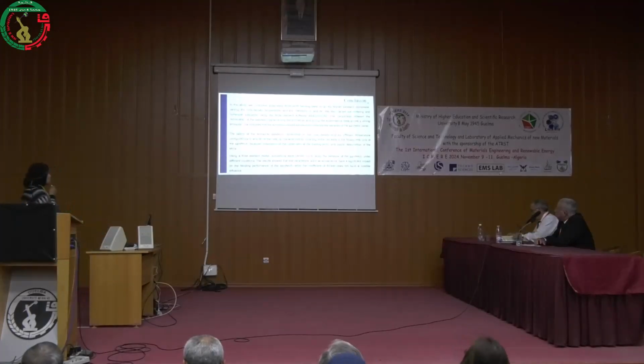So to sum up, in this study we conducted a quasi-static 3-point bending test on an aluminum Nomex sandwich composite, varying the core density, temperature and orientation L and W. We also carried out modeling and numerical simulation using the finite element software Abaqus. The comparison between the morphology of the sandwich panel during the simulation and during the experimental test shows a strong similarity. This indicates that the simulation results satisfactorily replicate the behavior of the sandwich panel.